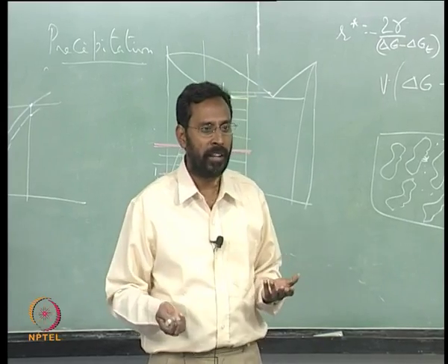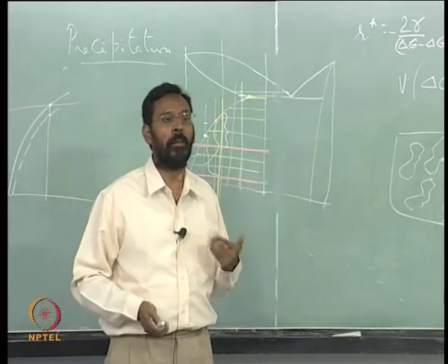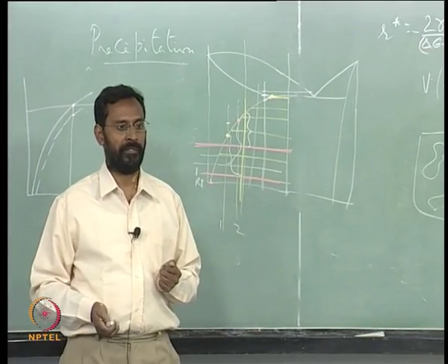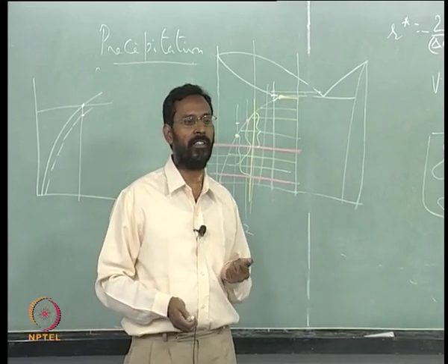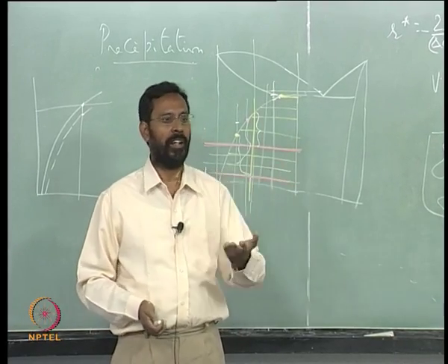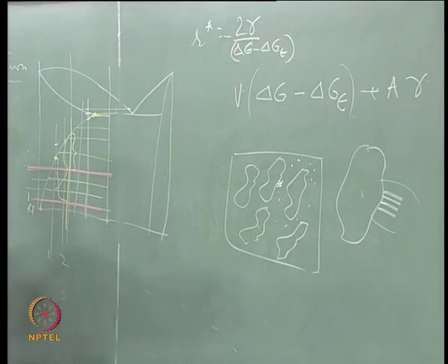Though copper atoms are there, sometimes you can get what are called metastable phases. For example, we have seen a number of cases where, when you are cooling, even in precipitation hardening, we see the GP zones, theta double prime, theta prime. These are all metastable phases, not the stable phases. The ultimate stable phase is the theta phase, am I right?